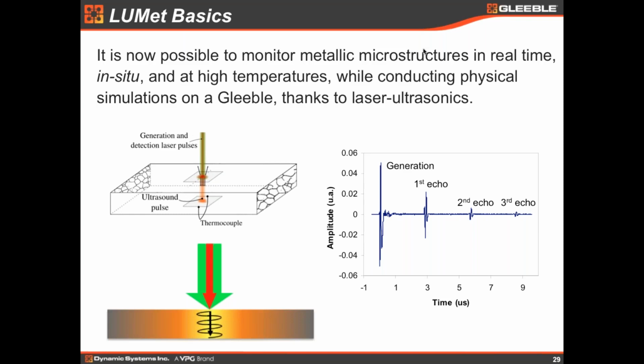There was a question, I believe, that asked if we could measure phase transformation with the Lumet. The answer there is absolutely yes, assuming that the phase transformation results in a different speed of sound. And obviously, a BCC is going to have a different speed of sound than an HCP or an FCC material. So typically a phase change will be accompanied by a very rapid change of the speed of sound of the material, and therefore the Lumet can pick that up very easily and very quickly.